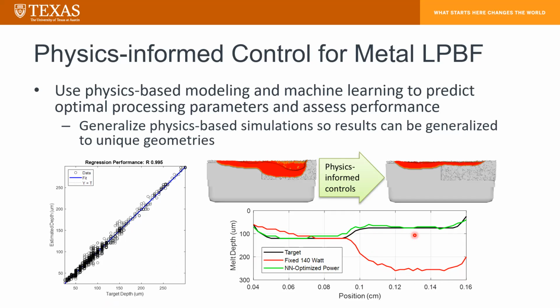But when we use our physics-informed controller, we get the results on the right. And on the bottom here, that green line is now our melt profile. You see there's really good agreement between that profile and our target melt depth. So again, using this process, we're able to have much more control over the outcome of these parts.